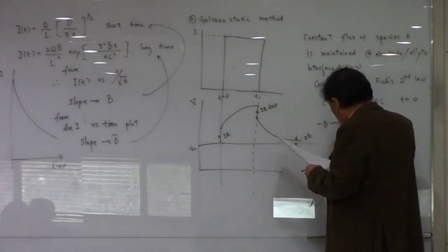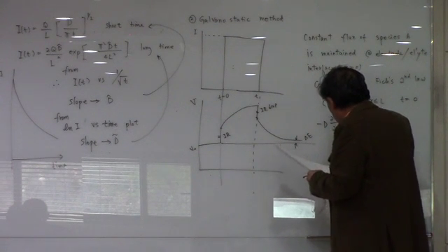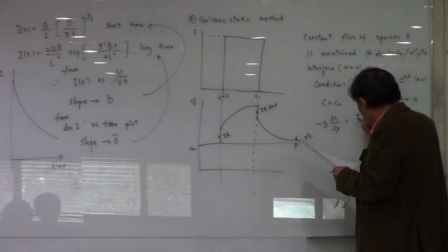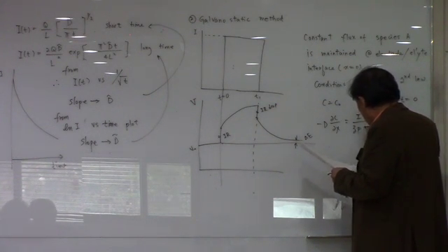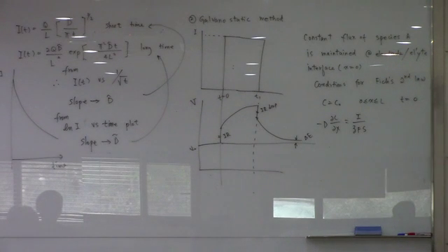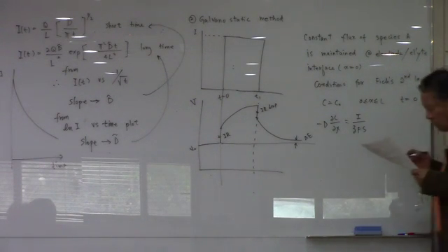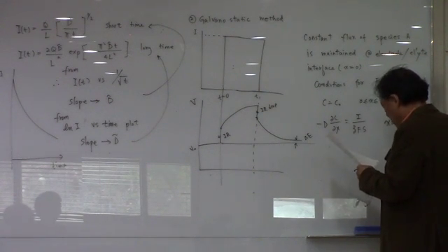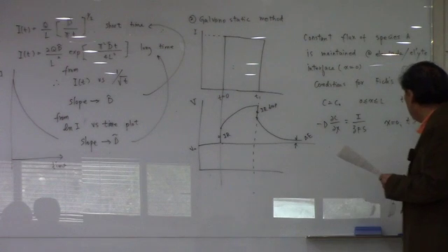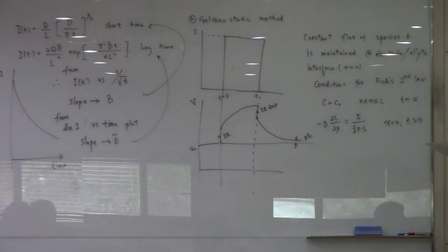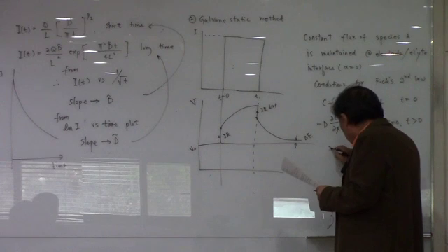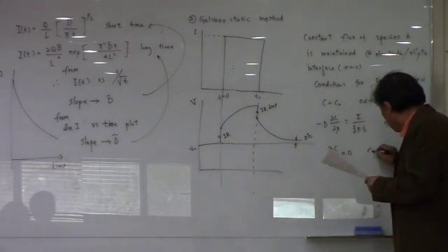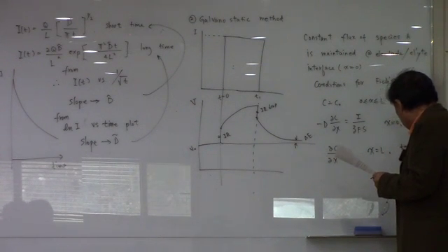And now you're going to apply constant current, which is related to the diffusion coefficient, the flux according to Fick's first law, at x equal to 0 for the time you begin to apply the current. Now again, at the end, you do not have any flux. Okay?